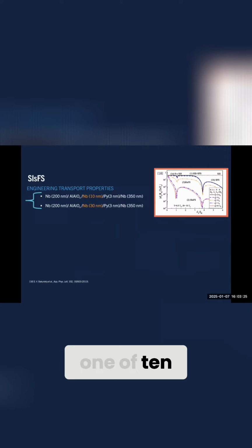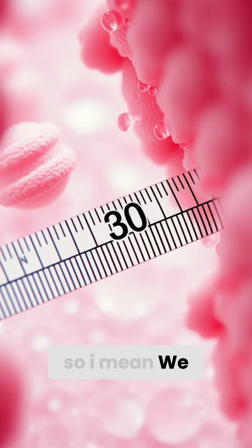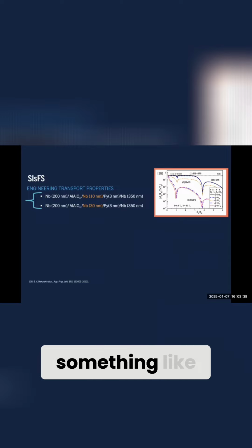We test for this configuration two thicknesses of niobium, one of 10 nanometers, so close to the coherence length that we expect for the niobium, polycrystalline niobium of our fabrication systems, and another one of the order of 30 nanometers. So we expect something like three times the coherence length of our niobium, and we use in both cases 3 nanometers of permalloy.